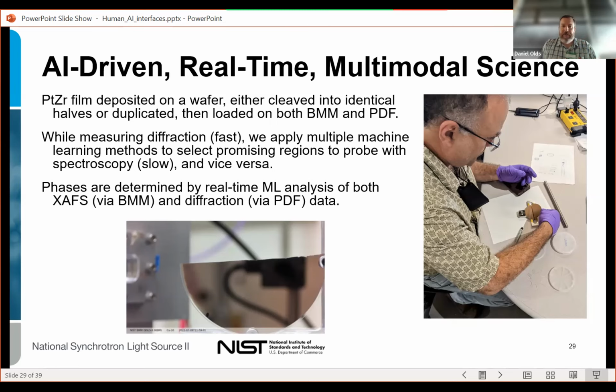The diffraction measurements are fast. The XAFS are slow. In addition to the fast diffraction, it could kick off PDF, which was a little bit slower because it had to move the detector and measure a bit longer.